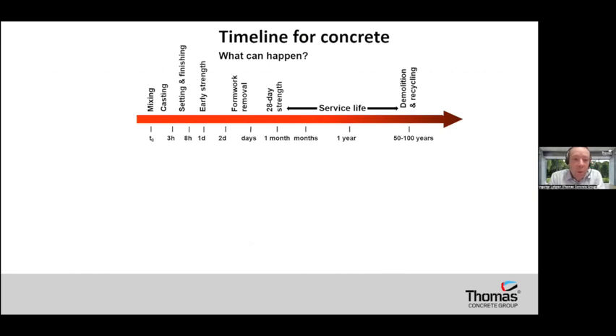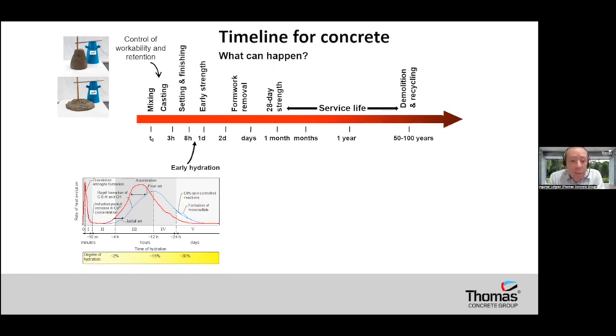And generally, when we look into concrete, we can look at the time from mixing up to end of life and recycling. In the beginning, control of workability and workability retention is very important, because the concrete needs to be mixed, transported to site, and cast. Then we come into what Ruben and also Liming talked about: during the first couple of hours not much happens, but then hydration starts and we have an increase of heat development, which is connected to the early strength. In this period we can also have problems with plastic shrinkage cracking in the fresh concrete.